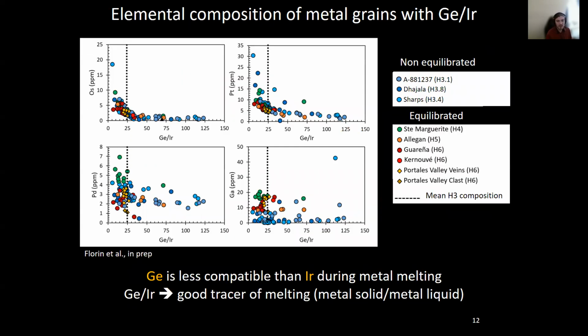If we now report our measurements against the germanium to iridium ratio, we can highlight an inverse correlation between highly siderophile elements and moderately siderophile elements and the germanium to iridium ratio. The striking point here is, as previously said, the large variation of composition from one grain to another. Regarding this correlation, we have developed a batch melting model to try to explain these two correlations.